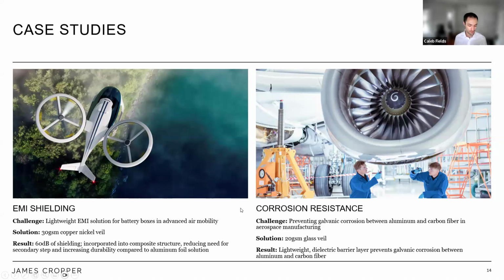So the final example I use here, as Mark mentioned, we have dielectric materials. Often galvanic corrosion is an issue, especially in aerospace when you have aluminum parts being bonded to carbon fiber parts. That's very prone to galvanic corrosion. So you need a lightweight solution because it's on an airplane, and you still need it to protect the aluminum from interacting with the carbon. So our 20 gram glass veil was used as a lightweight dielectric barrier to extend the life of the part and prevent galvanic corrosion.